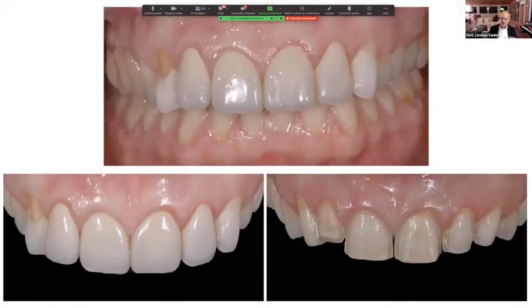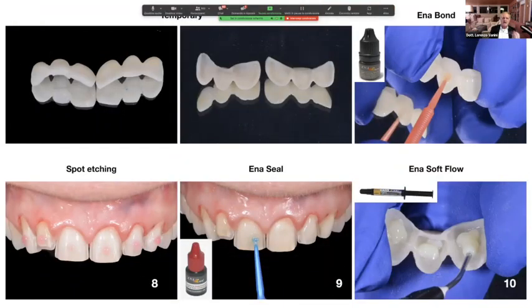So I show a clinical case. I have to remove these laminates. I re-prepare, and then I prepare the temporaries. I apply the temporaries, like I told before. You have to apply Enabond inside. You have to cure Enabond, because I want that when I remove the temporary, the cement, the Enaflow, stays in the temporary. This allows you to remove the cement completely, and you don't have to spend time cleaning the surfaces of the preparation.